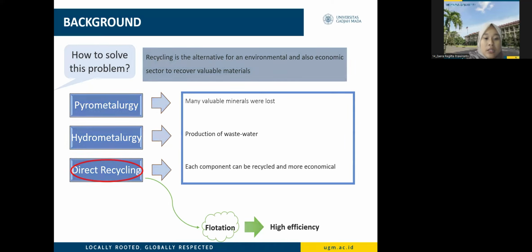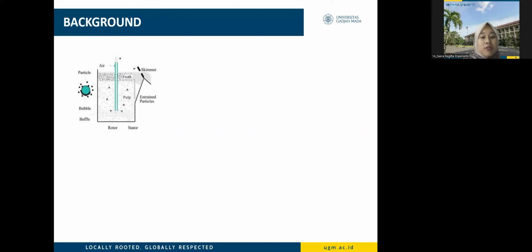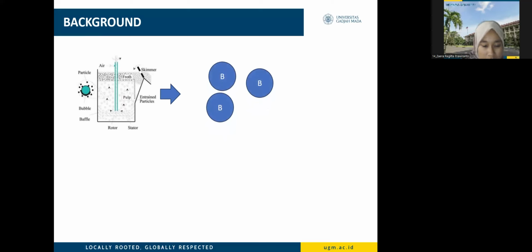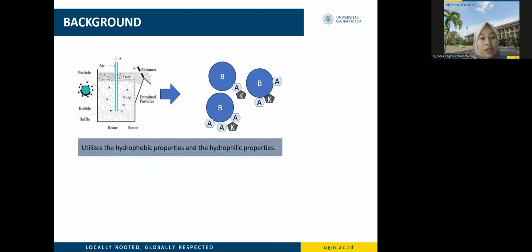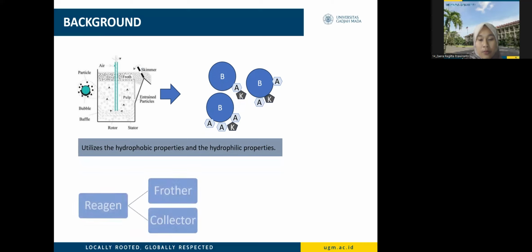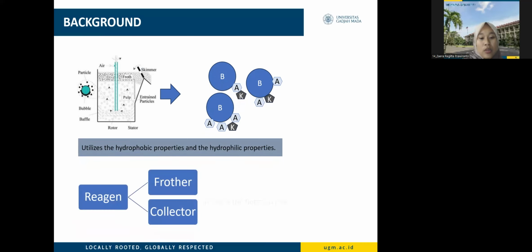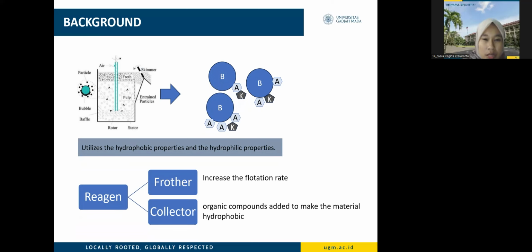What is flotation? Flotation is the process of separating or concentrating particles from other particles by using the principle of differences in surface properties, which are the hydrophobic and the hydrophilic properties. The hydrophobic particles separate by attaching themselves to the blown air bubbles added to the flotation column and rise to form a foam rich in hydrophobic particles. Reagents are an important aspect that needs to be considered in the flotation process. They function to increase the flotation process effectiveness.